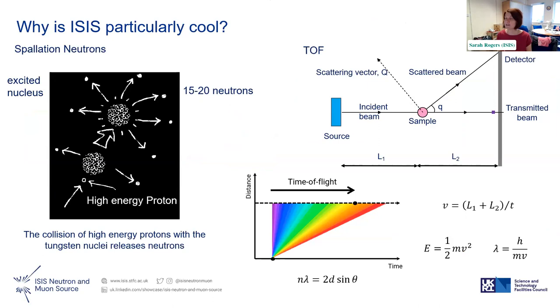I don't know if you know that ISIS is a spallation source, so we're not a reactor source. And basically what that means, I won't go into the full description of how we make neutrons. You can find that on the ISIS webpage if you're particularly interested. We basically take a beam of high energy protons and smash that into a heavy metal target. In our case, that heavy metal target is tungsten clad with tantalum. And when you do that, you basically smash neutrons out of it. And that's the spallation process.